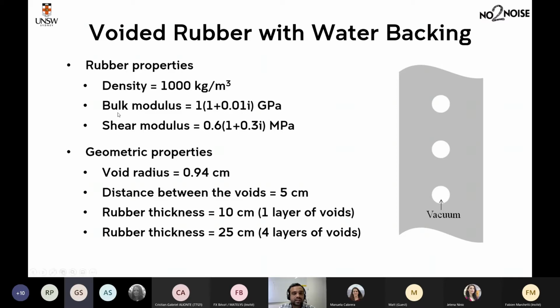You'll also notice that both bulk modulus and shear modulus values are complex. So the imaginary part here actually represents damping, right? In a real material, you always have damping. So it's really important to account for damping correctly. As you can see here, the bulk modulus of our soft rubber is much larger compared to the shear modulus, or I should say the other way. The shear modulus of rubber is much smaller compared to the bulk modulus, right? And this is one of the characteristics of soft media. The shear modulus is very small compared to bulk modulus.